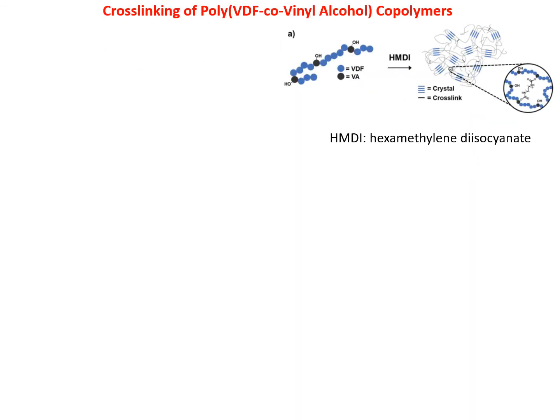So I would like also to mention a nice work from several groups regarding the cross-linking. Katja Loos in Groningen did the radical copolymerization of VDF with vinyl acetate, which was then hydrolyzed into vinyl alcohol. So you have a copolymer in which the blue balls are VDF, and then you have some vinyl alcohol incorporated here. And of course, from the alcohol, you can make some cross-linking with hexamethylene diisocyanate in order to prepare a cross-linked system. So between the chains, you have HMDI, which occurs.